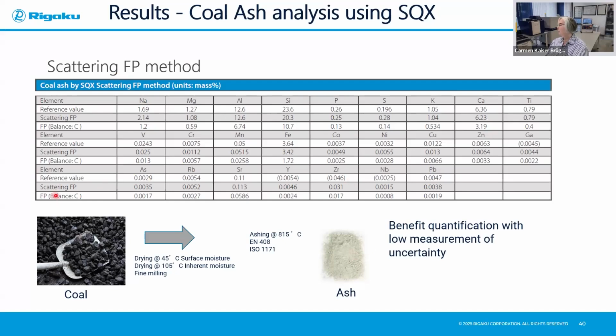So once again, we used the scattering FP method, and we combined it also with a comparison of just putting carbon as an input. So you can see from the results, for example, the reference value is 0.029% on arsenic. Using the scattering FP, we get 0.0035%, and setting carbon as a balance is 0.0017. So you can see 2 kinds of methods can be used for the analysis of trace elements and, of course, the lighter elements.